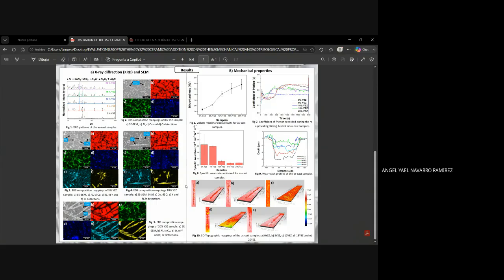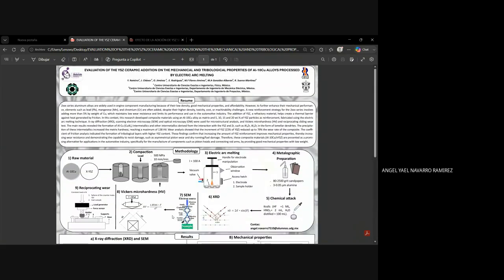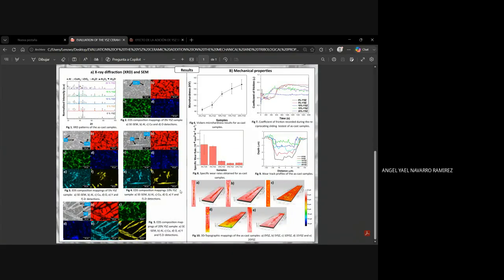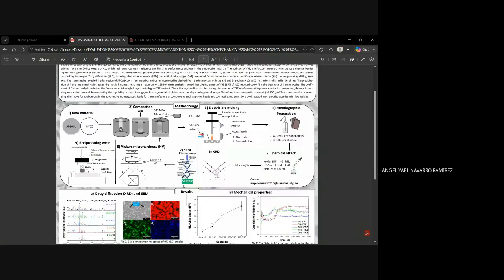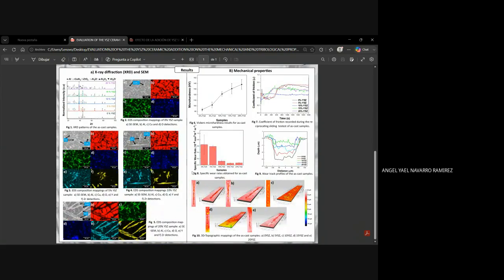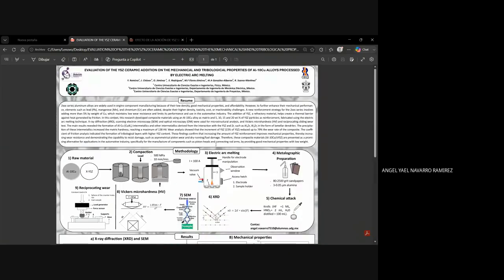This is actually my project, and I decide the best option for use in the automotive industry is 15% of YSZ, because it has very good microhardness, very good resistance to reciprocating wear, the lowest specific wear rate, and the smallest depth in the wear track profile. 10% is also acceptable. And this is all from me. Thank you very much.